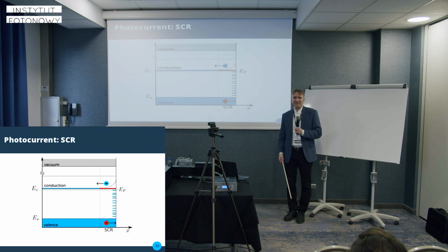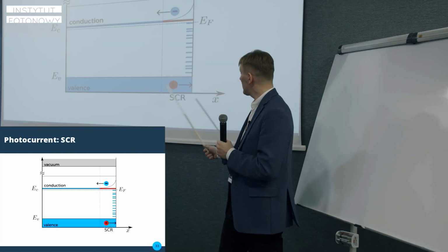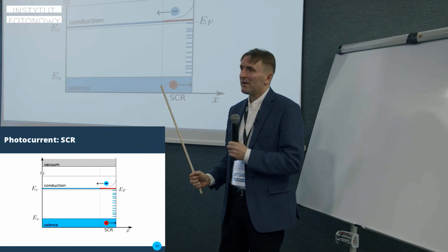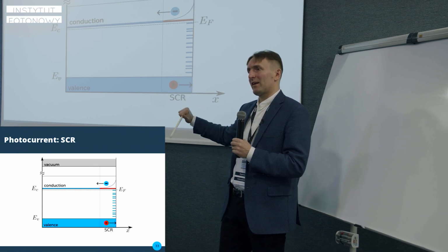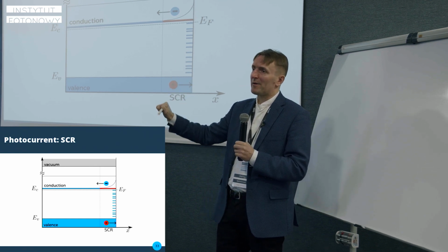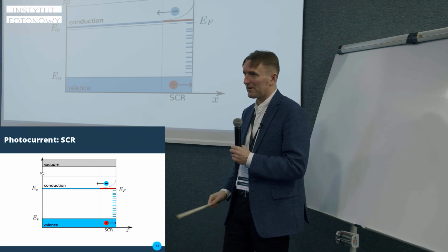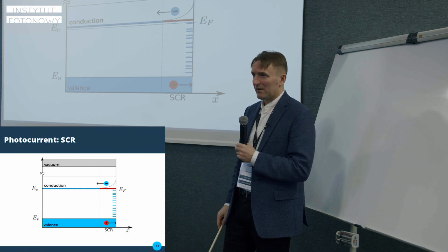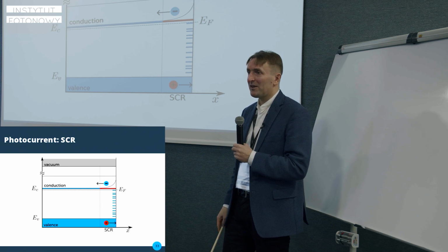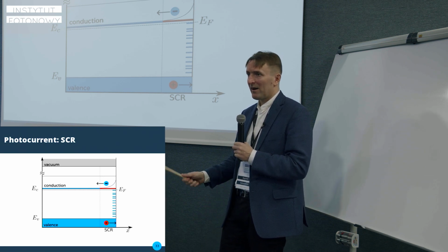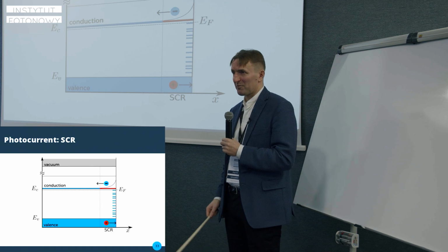The better answer is that the light does not enter the metal at all. If you have many carriers on the surface, they will adjust themselves to the electromagnetic wave coming in, and they will reflect it back. So this is perhaps the key reason why metals are not that good at producing photocurrents.